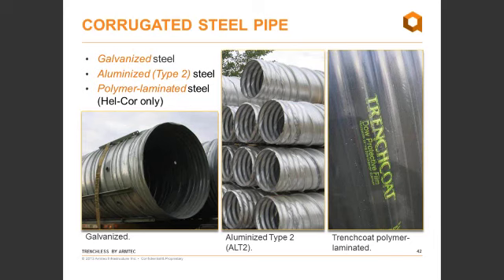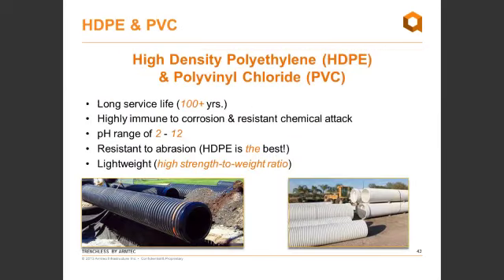pipe. So the one thing to keep in mind with any of the structural plates or the CSP pipe coatings is that, if you're in a case where abrasion or some kind of damage happens, once you lose the coating, then you have exposed steel, and then your service life is going to decrease a little bit. So that seems to be a good point where we can switch gears for a bit and talk about plastic pipes or plastic products, and we're going to focus on our trenchless or relining operations.